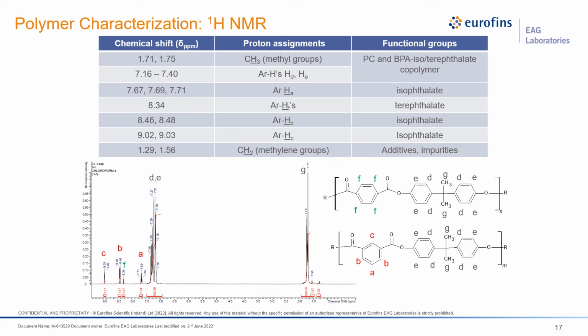On the bottom right of the slide, we see two different structures. On the top is the terephthalate, and on the bottom is the isophthalate. For the terephthalate, there are 4 protons that are labeled F. These are all chemically equivalent due to the symmetry of the molecule, and they only collapse to create one peak in the sample spectrum. On the other hand, the isophthalate, which also contains some degrees of symmetry, but not quite as much, ends up producing 3 signals in our spectrum.